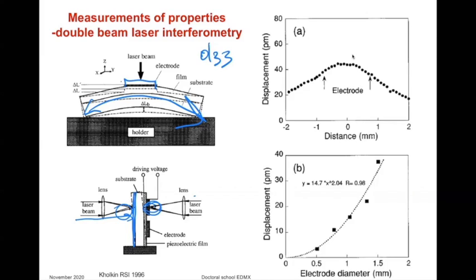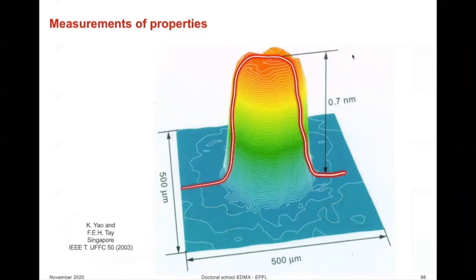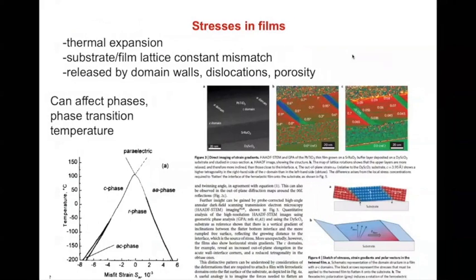This sort of experiment depends very much on the width of the electrodes, and it turns out there is an optimal lateral size of the electrodes to reduce these extra effects. Usually you have to do some finite element modeling to understand this. One doesn't have to use a double-beam interferometer — our colleagues in Singapore have developed a different way of doing that, which eliminates bending of the substrate from the piezoelectric film deformation under electric field.